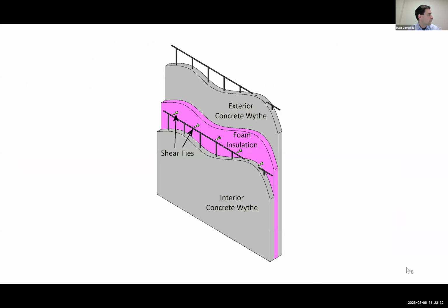And here's just one example of a specific precast component that I've worked a lot on. It's called a precast insulated wall panel. So it's got two concrete wythes, which can be pre-stressed or non-pre-stressed, but mostly pre-stressed. And there's a layer of insulation in the middle that helps improve the R value, thermal resistance of the wall. But in order to make the wall behave compositely and have benefits for checking stresses and deflections, we connect the two concrete wythes with connectors. And those connectors are usually made of polymers to help further reduce the transmission of thermal energy across the structure. And I've done a lot of work on the testing of those connectors and developing design standards for insulated wall panels in general, which I'll talk a little bit about at the end.